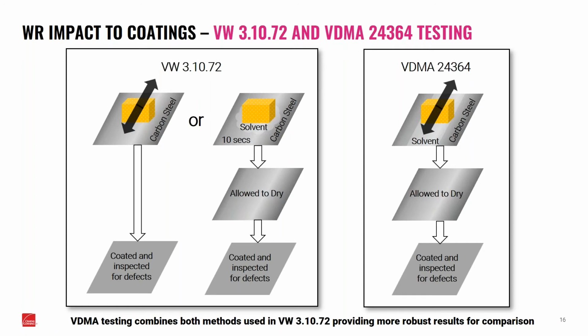Now, what this new VDMA test does is it essentially looked at this previous method and thought, well, why don't we just combine the two so we don't have to specify whether we did the dry method or the solvent method. The VDMA method is pretty extensive, and there are more details in our technical bulletin. But for the test that was used for this comparison, it was simply combining both, where you're actually scrubbing the insulation across the surface of the carbon steel in solvent to make sure that any agent that is in that insulation is going to be released and dissolved into that solvent. You allow it to dry, and then you coat it, and then look for defects.